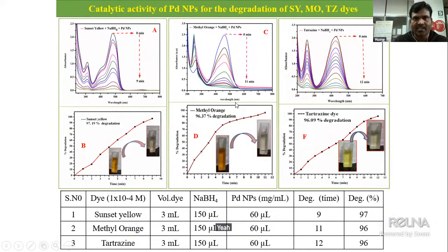So this is the catalytic reduction of the dyes. We are taking different azo dyes: sunset yellow and methyl orange, tartrazine. These are the food dyes we used. Here, for all the dyes, the absorbance value decreases in the presence of the extract, with a gradual decrease in the absorbance. We can clearly notice the dyes undergo decolorization after a certain period, so a reduction reaction occurs in the presence of the extract and sodium borohydride.